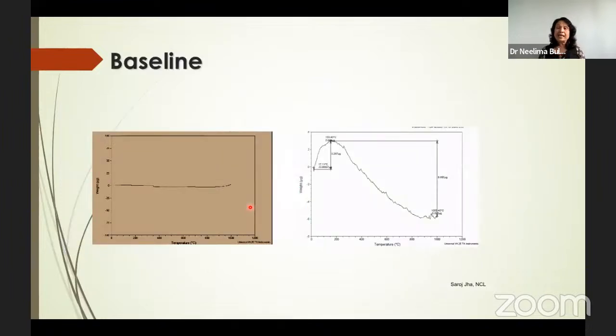Second thing is this baseline calibration is important, because in thermal analysis, in any experiment you do, your baseline should be straight. Suppose the previous user has left something, and his material is there at the bottom of your TGA furnace or sample holder, and it's an invisible sample. If you are in a hurry, put in your sample weight and start your experiment, and that previous user's material starts interfering in your data, you will land up with the wrong information.